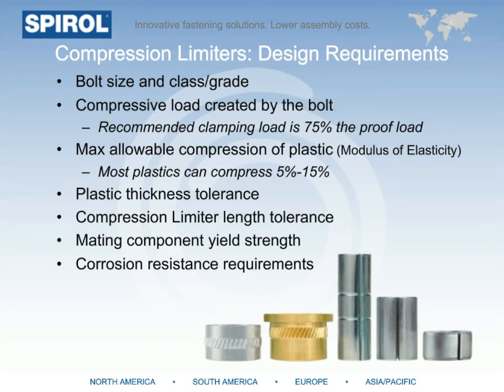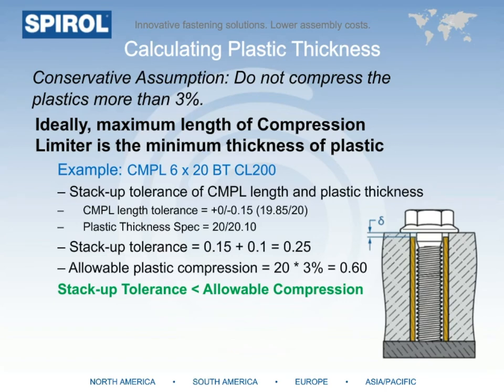So here's an example of how we use some of the information that we just talked about. If we don't have any information about the plastic's modulus of elasticity, we'll typically assume a conservative compression amount of 3% of the plastic. In this example, the customer is early in the design stage and has selected our M6 by 20 millimeter long compression limiter, and they're looking for our feedback on the plastic thickness tolerance. Now remember, there are two rules for compression limiter length as it relates to the plastic thickness. The compression limiter must bottom out against the mating component and the bolt's head or washer once the bolt is tightened. And ideally, the plastic has a slight amount of compression when the bolt is tightened.